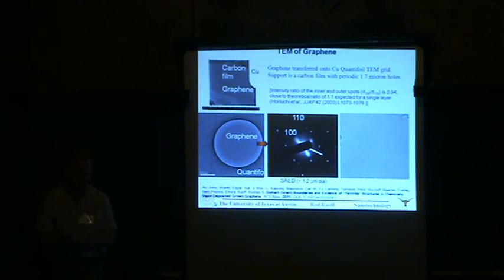We used transmission electron microscopy as well. One of the reasons for using TEM is, of course, it gives us an atomic scale view. But I think you can envision the challenge of finding the grain boundaries. So my group's approach has been divide and conquer. We have relatively large grain size material. That means we look in one area, select the area of electron diffraction, and keep moving around until we see a rotation. We know the grain boundary is somewhere between, try to find it,